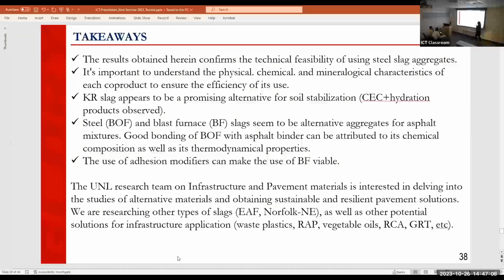We observed a better bonding of BOF slag with binder, which could be attributed to the presence of ferrous components and calcium oxide, and also because of its thermodynamical properties. But BF is still viable if we add some additional modifiers.